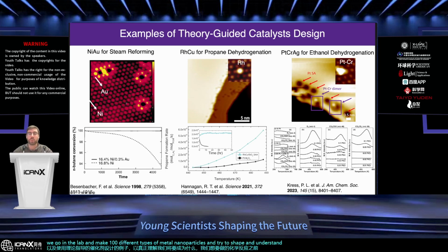And so a couple of these where theory was used to predict catalyst design are nickel gold for steam reforming, rhodium copper for propane dehydrogenation, and again, the one that I had mentioned before, the platinum chromium on silver for ethanol dehydrogenation, which again could be really useful for, let's say, the generation of clean hydrogen from a bio-derived source. All right, so a lot of opportunities here.